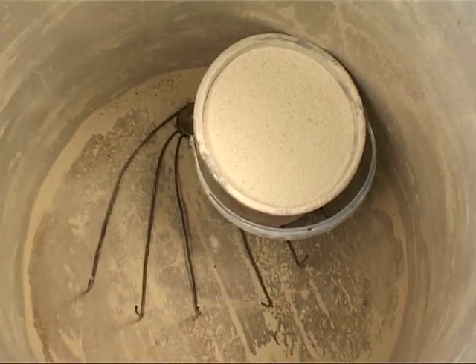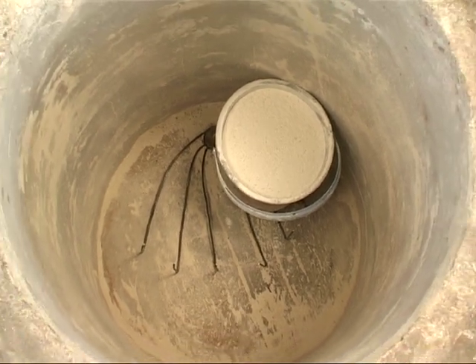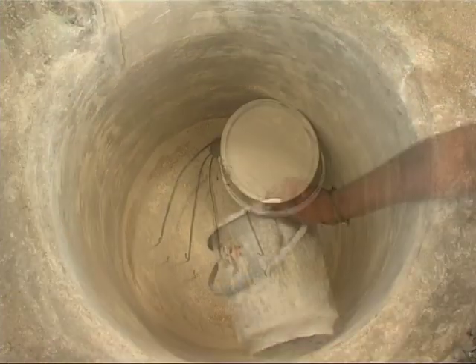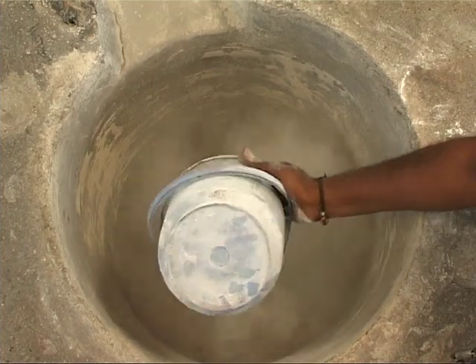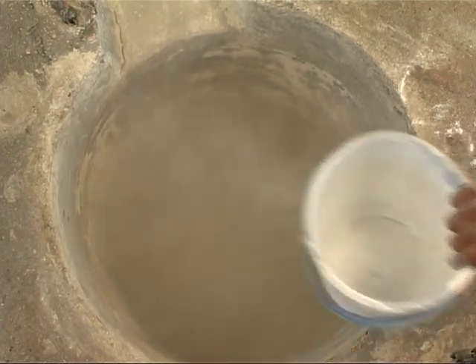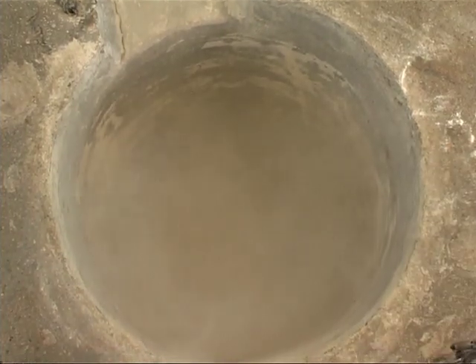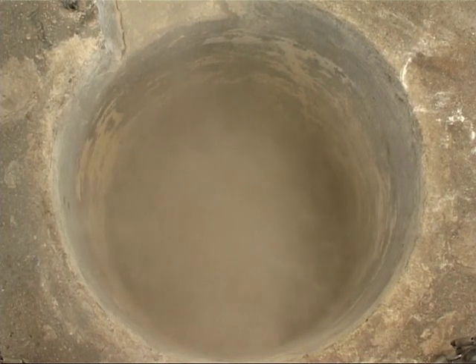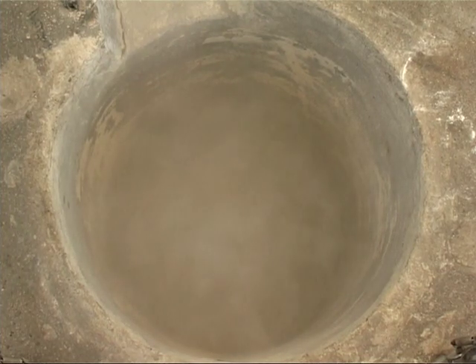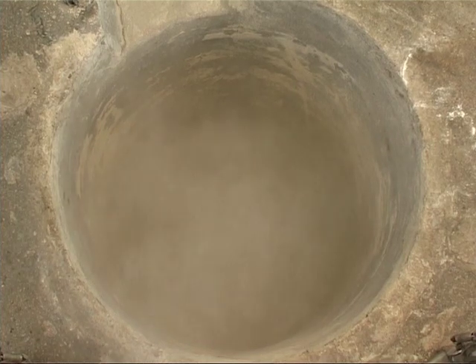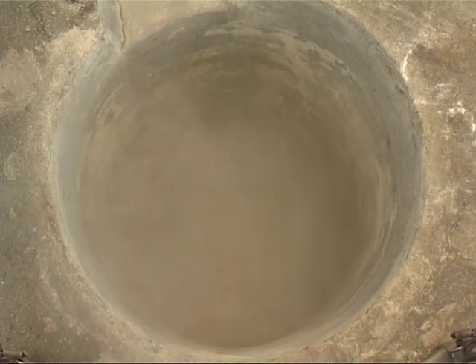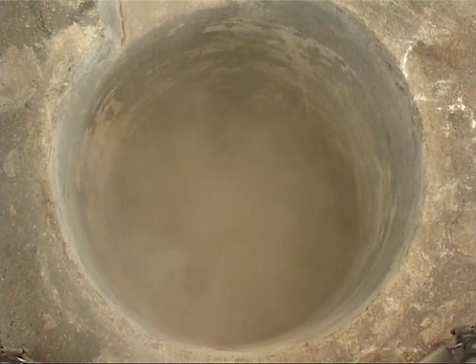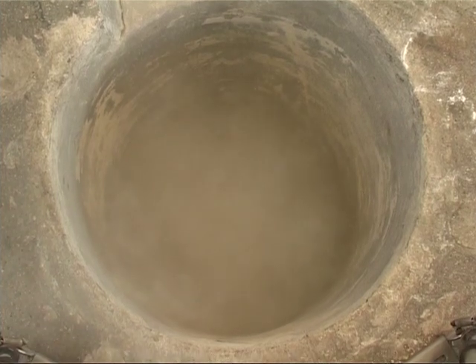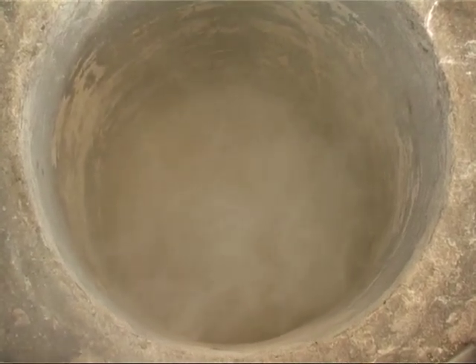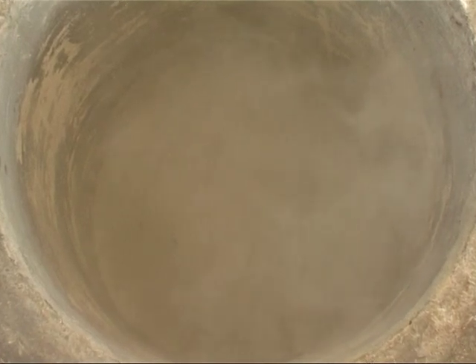Carefully place a 100 to 150 mm layer of the prepared ramming mix on the furnace bottom, with buckets lowered to the furnace bottom. It is recommended to use ramming mass without boric acid for 50% of the height of the lower portion of the furnace bottom. This avoids total sintering of the furnace bottom and reduces the possibility of metal leakage from the bottom.